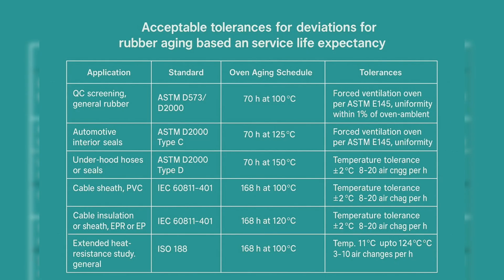After aging, you take the samples out, cool them at room temperature, and immediately remeasure the same properties you measured before. The change tells you the story. A small hardness increase and a 10 to 20% drop in elongation are normal, but big changes, say over 30% loss in elongation or tensile, show that oxidation is really breaking chains and tightening the network. That is why most standards like ISO 188 or ASTM D573 use a 30% deviation limit to decide if a compound passes or fails. It's not random. It's based on where visible brittleness usually begins.